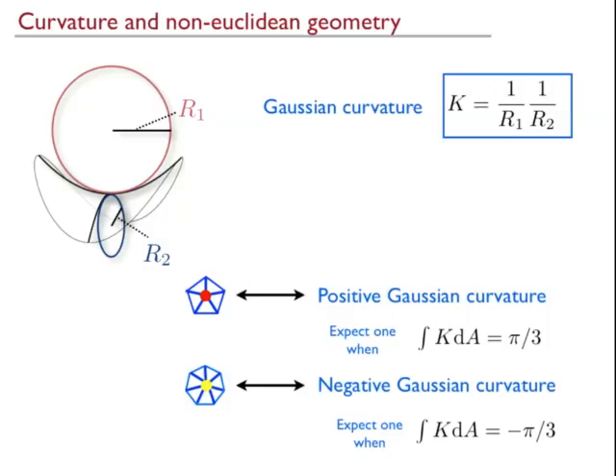How would you measure curvature on a surface? So what you do is you draw yourself a circle with a certain radius, right? And if the circumference of the circle that you draw with that radius is 2 pi times the radius, then you're in flat space. If you're on a sphere, and you walk down from the pole, and you draw a circle, if the circumference is less than 2 pi times that radius that you've walked, you have positive curvature, and if it's more, you have negative curvature.